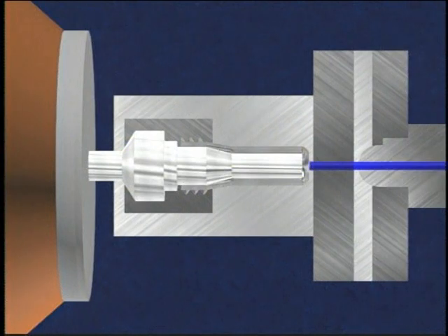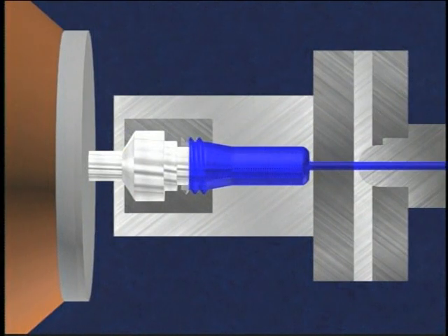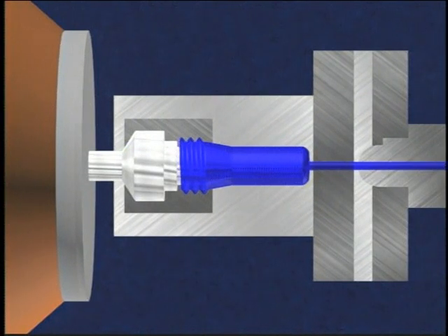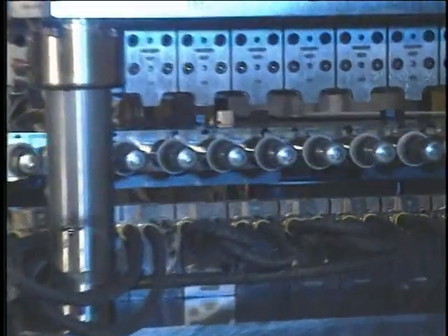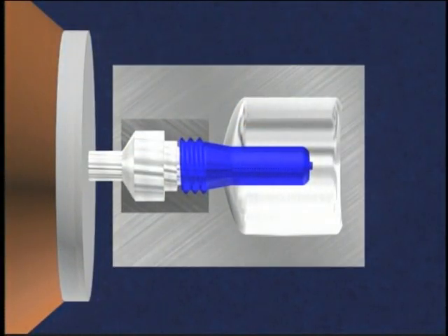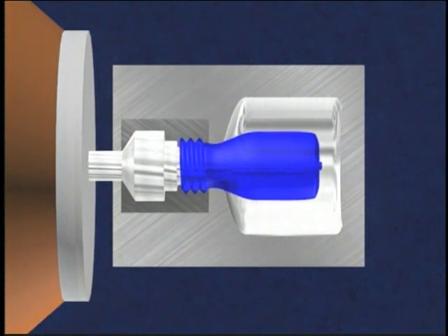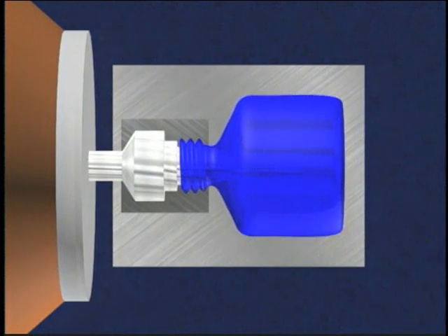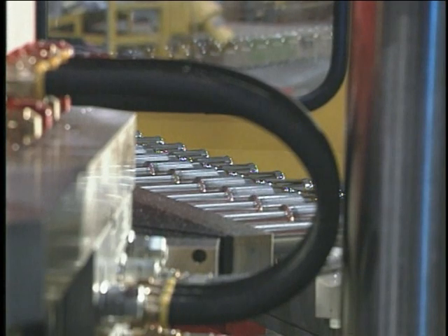The injection station is basically an injection molding machine. A RAM, usually a reciprocating screw, forces the melted thermoplastic resin under pressure onto a metal core rod held within a closed split parison cavity injection mold. After the outside skin of the parison has set, the parison mold opens and the core rod carrying the parison rotates to the blow station. Once the core rod is in position, the blow mold closes. A trigger bar opens the core rod air passage. The air lifts the parison from the core rod, except where it is held at the neck, and expands it to the shape defined by the blow mold cavity. Once the part has cooled sufficiently, the blow mold opens and the part is indexed to the next station for stripping or ejection.